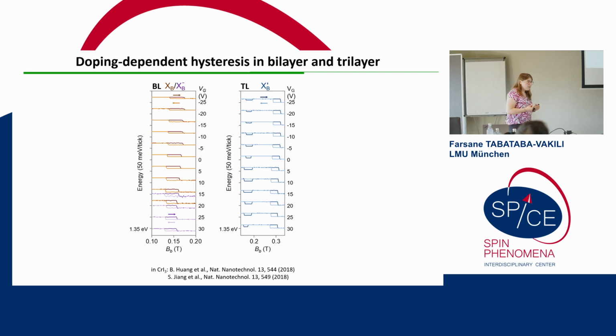And this critical magnetic field of the spin flip transition shows a doping dependence and also a hysteresis. So if we reverse the magnetic field direction, the critical field is a different value, and then if we dope, we see that this hysteresis loop shifts to smaller magnetic fields. And this is because the interlayer exchange energy is inversely dependent on on-site Coulomb interaction. So as we dope, we increase the Coulomb interaction, and with that, we reduce interlayer exchange energy, and with that, we reduce the critical magnetic field. And similar results were shown a few years ago in chromium triiodide, where they also showed a doping dependence of the magnetization.